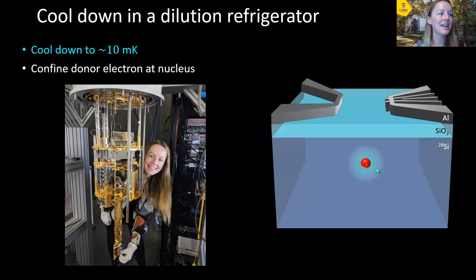So we then get our enclosure containing this printed circuit board with our quantum device inside, and we mount it onto a dilution refrigerator that can cool our device down to around 10 millikelvin, or 1/100th of a degree above absolute zero, which is about 300 times colder than outer space. So it's very cold. And at these temperatures, our donor electron will be bound to our donor nucleus. Shown here is an image of one of our dilution refrigerators in Sydney in the group of Professor Andrea Morello. And there I am next to it to demonstrate the scale of the fridge.